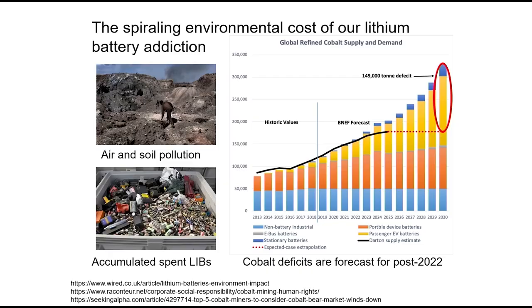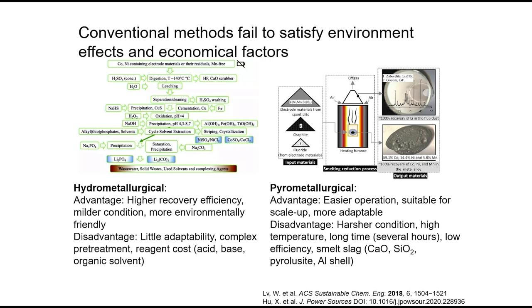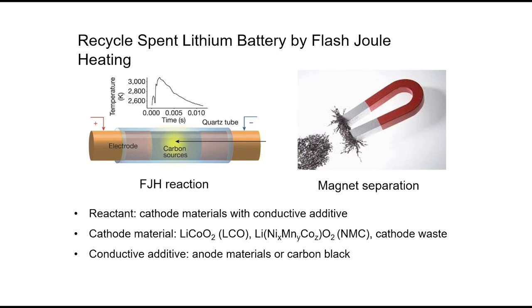There's only 5% of lithium-ion batteries being recycled — it's a mess. If you use the hydrometallurgical method you're using 15 molar concentrated acids and lots of water. Pyrometallurgical requires big furnaces with huge amounts of energy. What we found is we just flash the cathode waste. Whatever is magnetic is what you want — we get the cathode back out, and it is a better cathode. We put these into batteries and they perform better than the original. That's because flashing creates a conductive carbon coat over the surface that is lithium-ion permeable — something that normally requires additional processing steps.